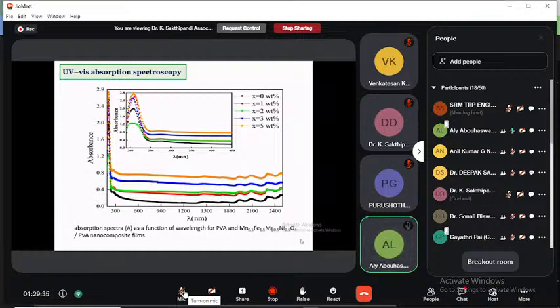And as the wavelength increases beyond 1500 nanometer, we observed multiple absorption peaks for spinel ferrite, and this oscillation is due to interaction between the polymer matrix and the incident light. The value of the observed linear optical absorption was elevated by doping with nanoparticles, and the absorption value increased as nanoparticles increase in the polymer matrix, with a small shift to longer wavelengths of the absorption edge. This shift is translated into a change in the energy band gap and the band of optical transmission, as we will show later.